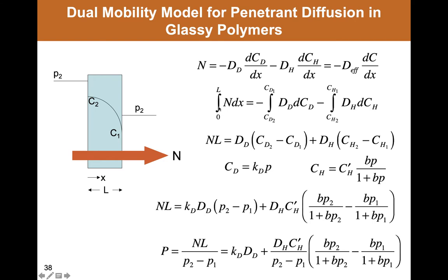One can integrate the general flux expression. I won't go into all of the details. This is just to show you how models like this are set up, where there are multiple pathways for transport through a material. And the bottom line for steady state transport, that is permeability, which is the flux through the membrane times thickness divided by the pressure difference that brings about that transport. And there's a typo here on the right hand side. This P2 should be P1. And so this is the general expression for permeability of a gas through a polymer under the dual mode assumption.